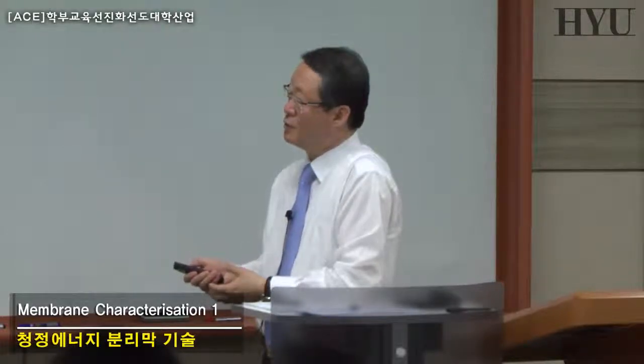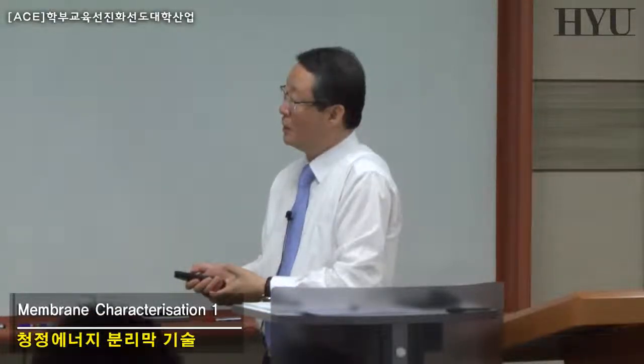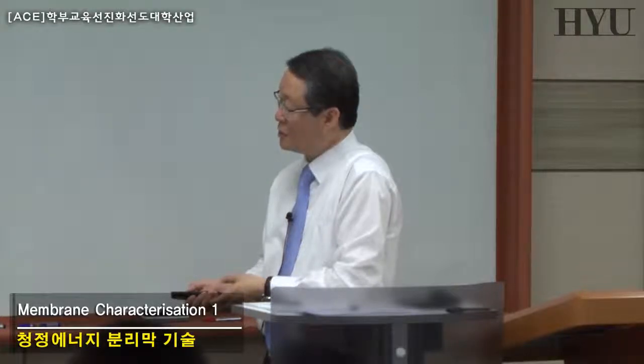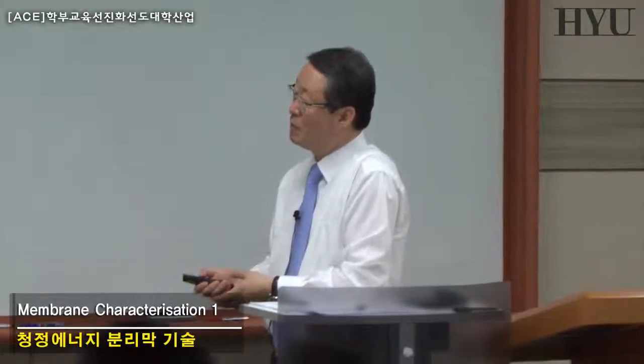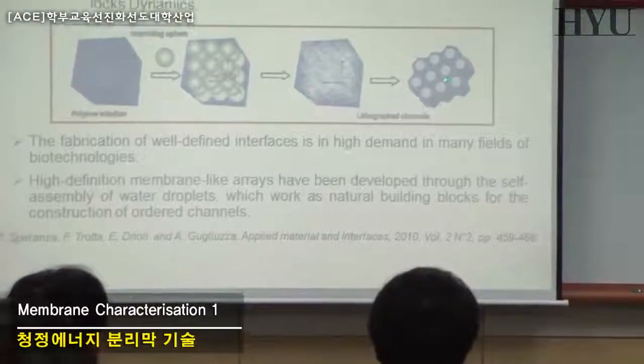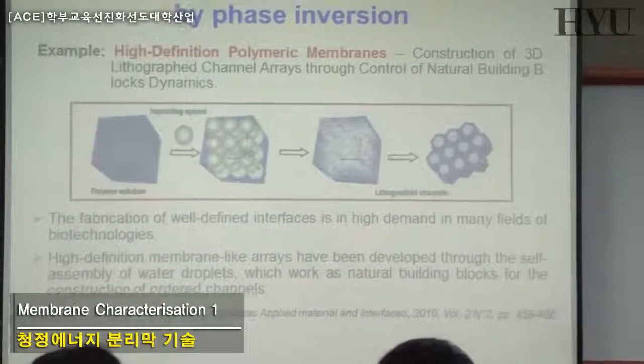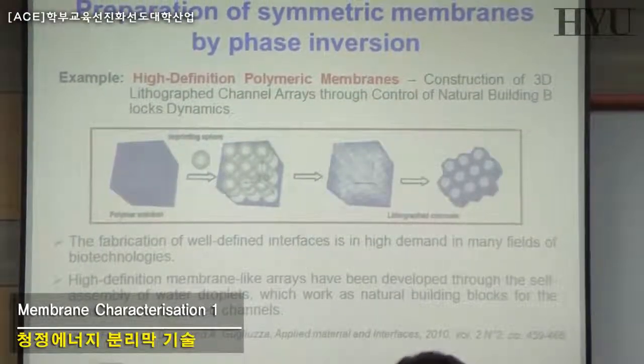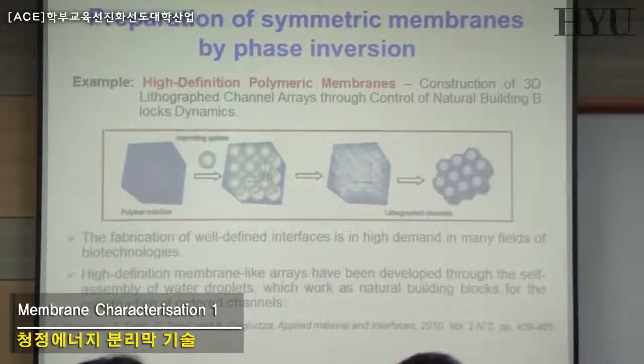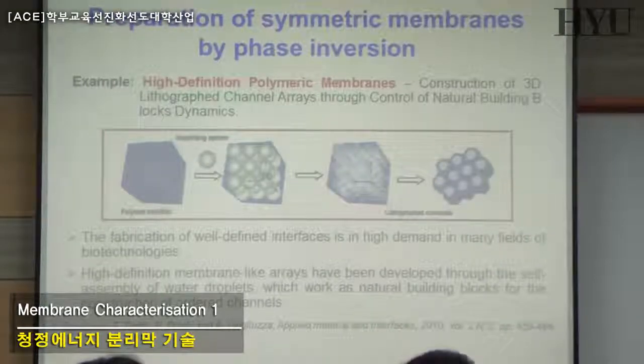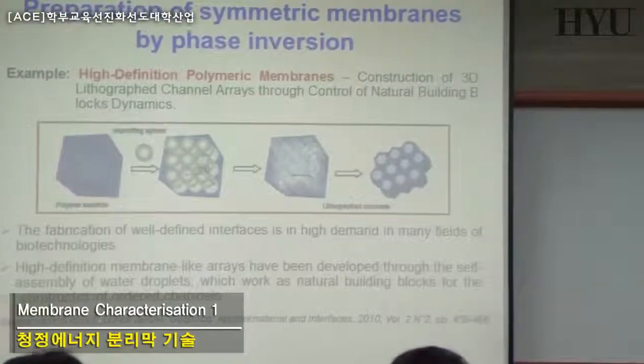What you could do is that you could use a non-conventional, high-tech lithographic technique to prepare the porous membrane, starting from your polymer solution. And this was published a couple of years ago. What they have done is that they put the mask and photosensitize them to make the porous membrane with very defined pores, which is not the same as the track-etched membrane that you have seen. The track-etched membrane has a very randomly oriented porous structure, whereas if you're using this high-tech membrane preparation method, you can make a very nicely aligned membrane with nice pores.